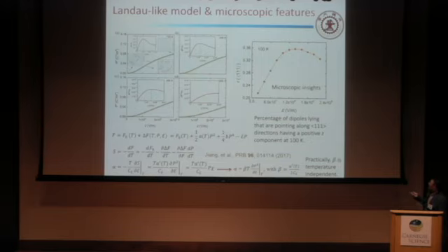From the picture, we can see that the ratio of the percentage of dipoles as a function of electric field has a peak around 1.2 by 10^8. This peak is associated with the EC coefficient as a function of electric field. In other words, by calculating the percentage of dipoles lying along different directions, we can understand the microscopic insight, the rearrangement of the dipoles, to understand the EC response.